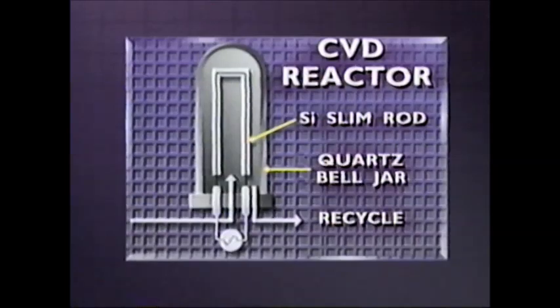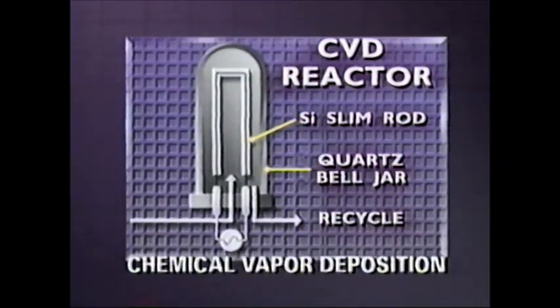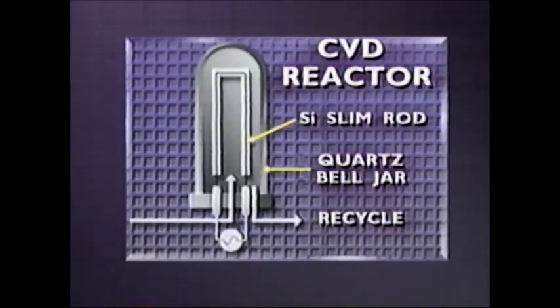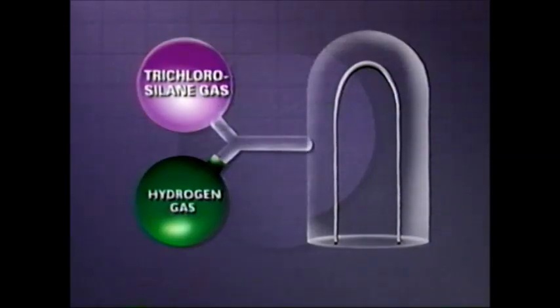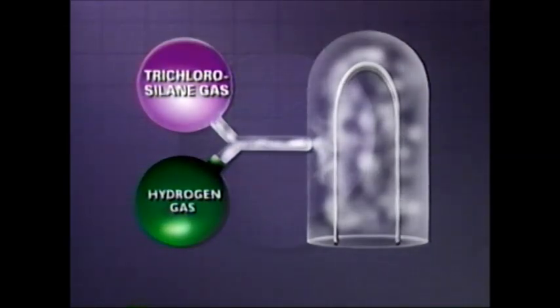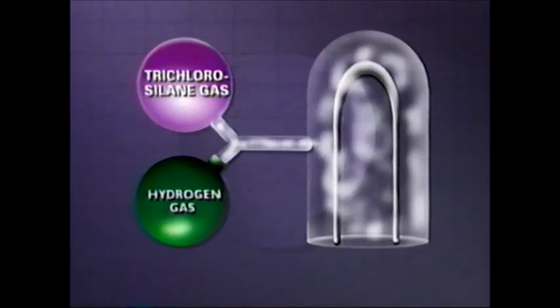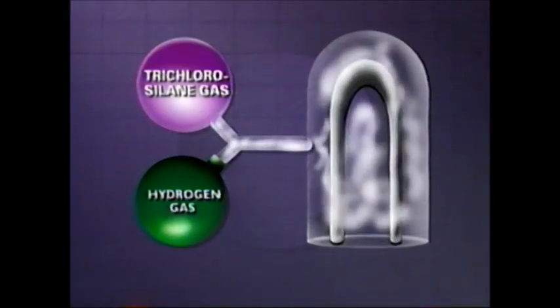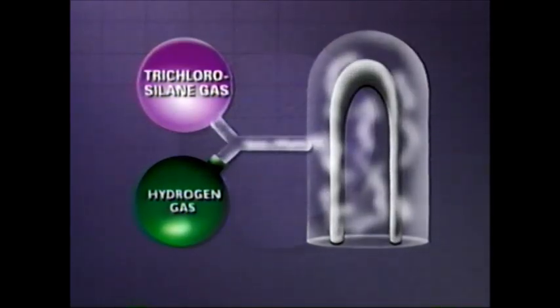To make EGS from the trichlorosilane, a process called chemical vapor deposition is employed. A slim rod, which is a heated rod of silicon, is used as a nucleation point for the deposition of pure polysilicon, that is, pure silicon which does not have a regular crystalline structure. When a mixture of trichlorosilane gas and hydrogen gas flows over the slim rod, EGS builds up or grows over many hours until the desired thickness is obtained.